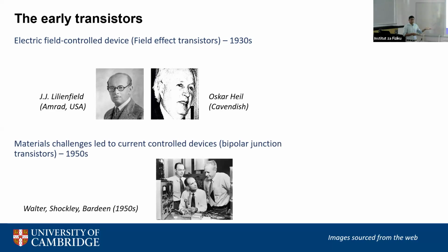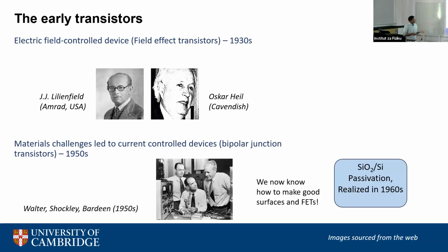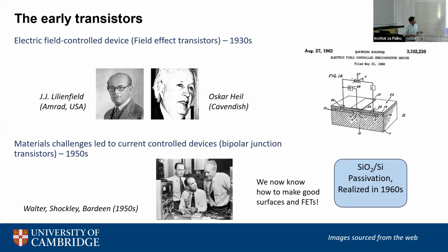What enabled the field effect transistor was the ability in materials engineering to make good surfaces. The breakthrough was silicon oxide passivation. So Dawon Kahng had this patent in '63, where they showed that you can grow very nice silicon oxide on silicon. And that is an ideal dielectric interface with silicon, semiconductor, silicon oxide, across which you can apply a uniform electric field. Only after this discovery in '63, we started having field effect transistors.